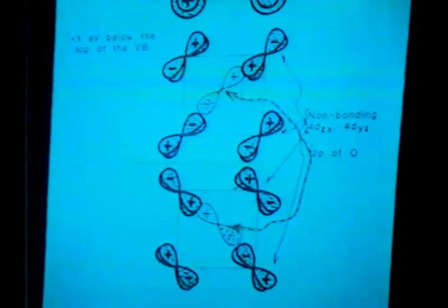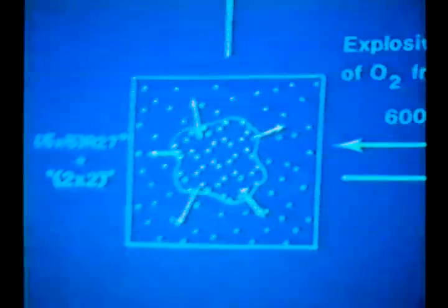So what we have a picture of now is that the oxygen binds to the surface specifically with the antisymmetrically positioned DZX and DYZ orbitals, and then deep into the crystal, this kind of interaction propagates 2, 3, 4 layers with decaying intensity by interactions of these orbitals with inside orbitals, and further interaction with the core level 3D. Next slide.